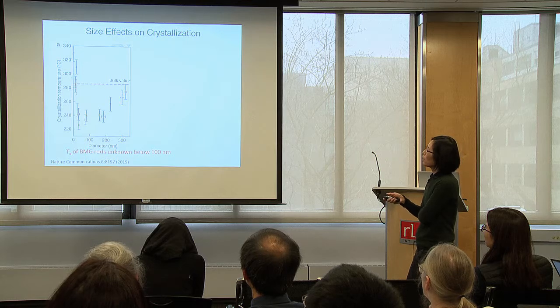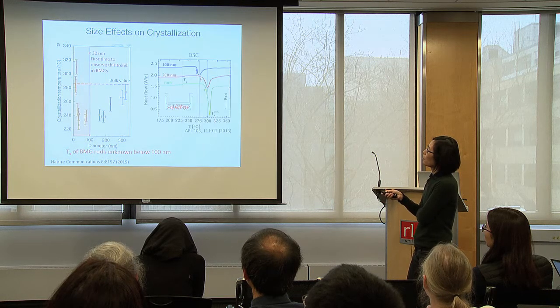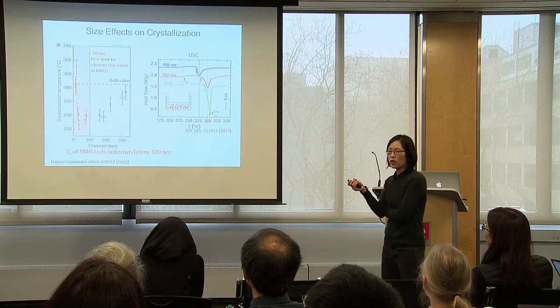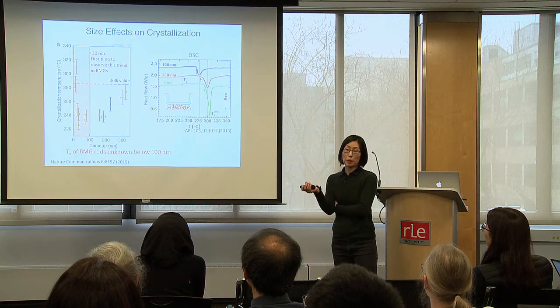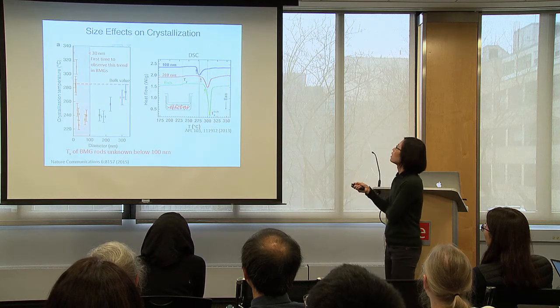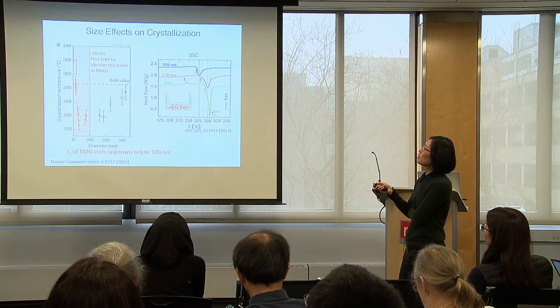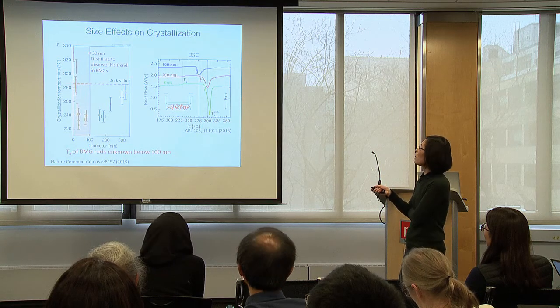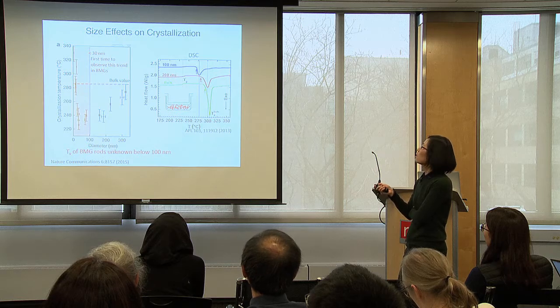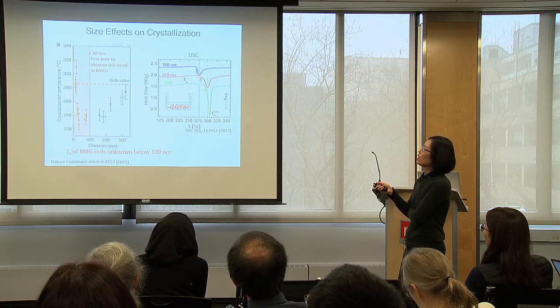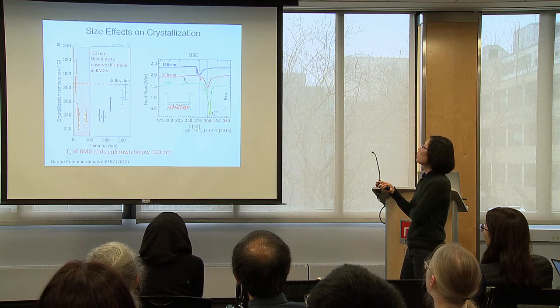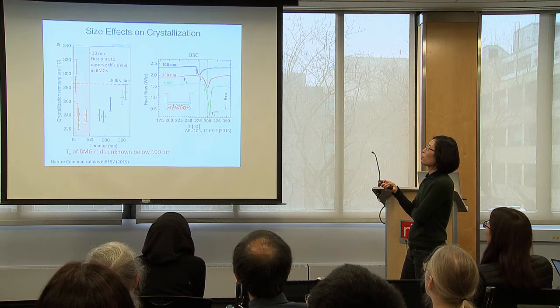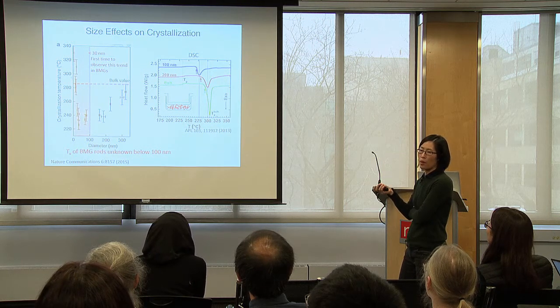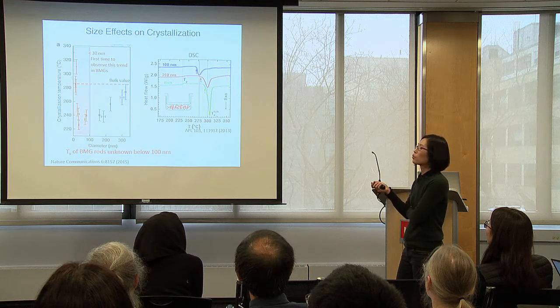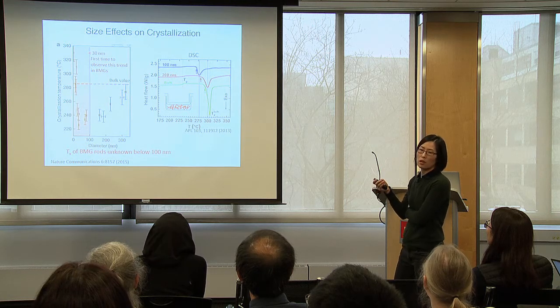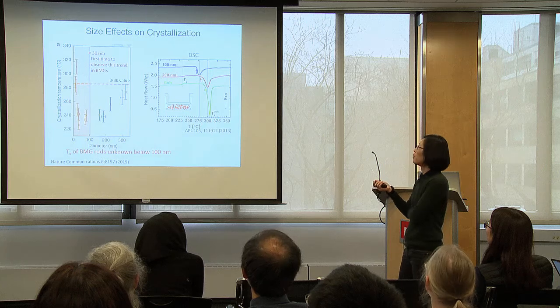Before this study, there were traditional differential scanning calorimetry experiments done on nanorods, where they collect many 200 nanometer rods, and then you look for when it crystallizes. The challenge here is signal-to-noise ratio. To have a reasonable signal-to-noise ratio for 100 nanometer rod diameter, you need billions of them. So if you were to do this for smaller rods, that's a very difficult experiment.